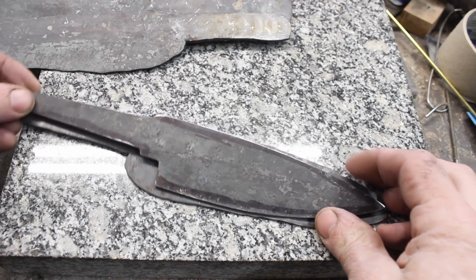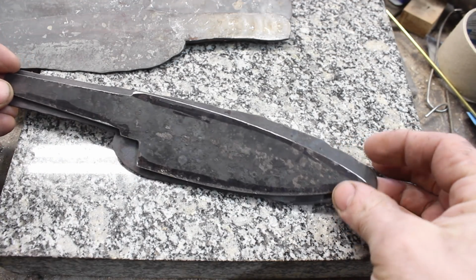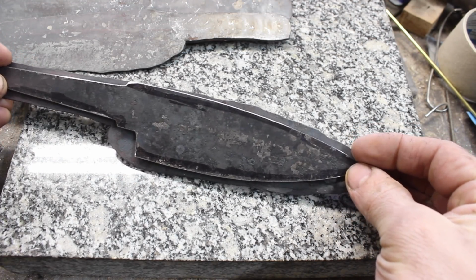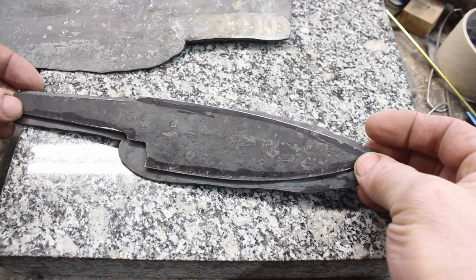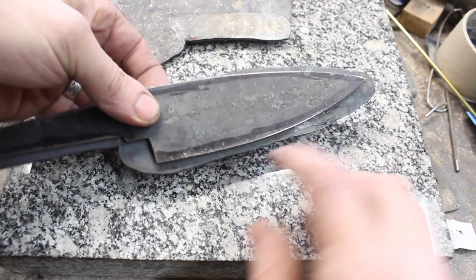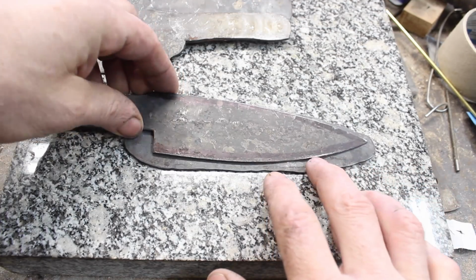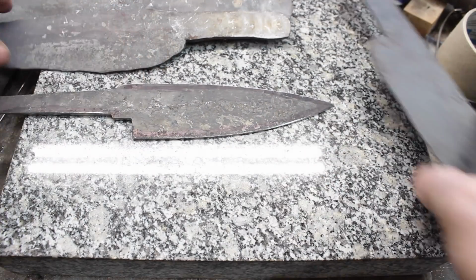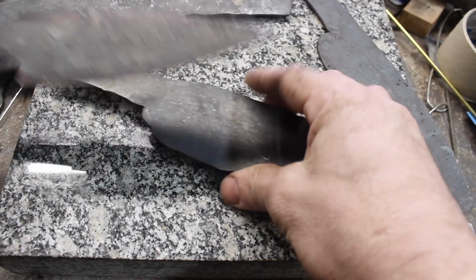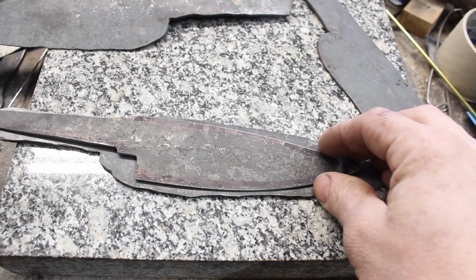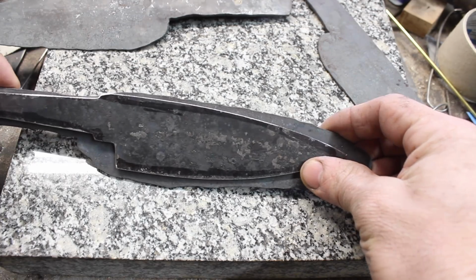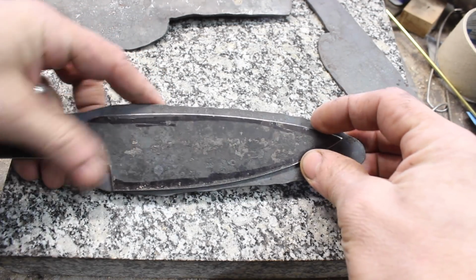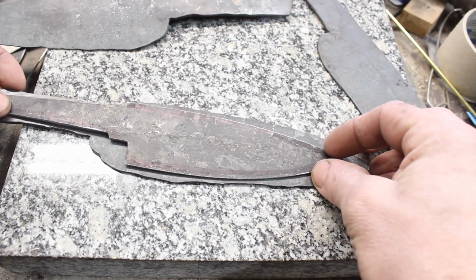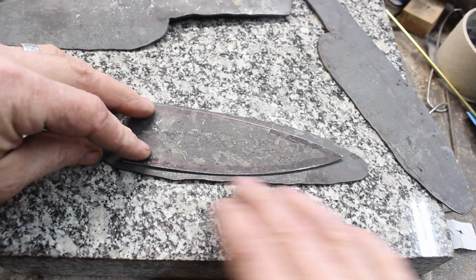Now that we have the profile defined on our first knife here, I can use it as a template for the other three. And you'll notice that I am staying away from the edge of our forged blade here. As I mentioned earlier, the propensity for the edges of the billet and the ends of the billet to not fully forge weld is very common. It's just kind of part of the deal. So that'll keep us away from that.